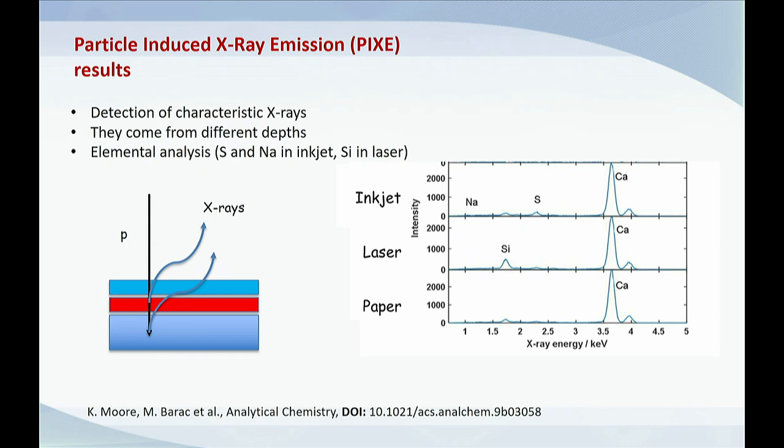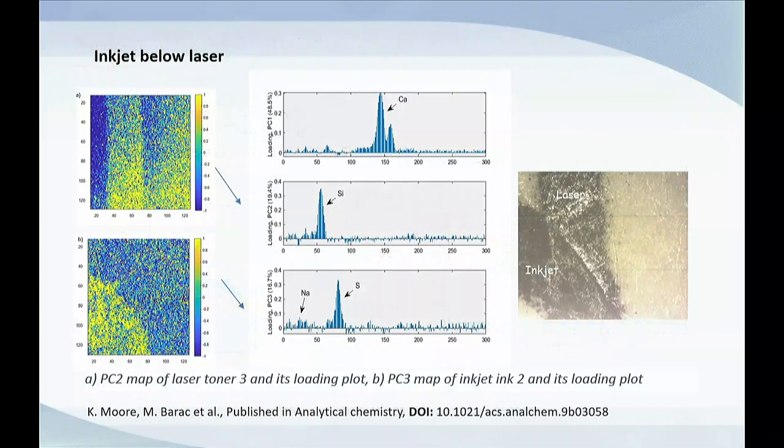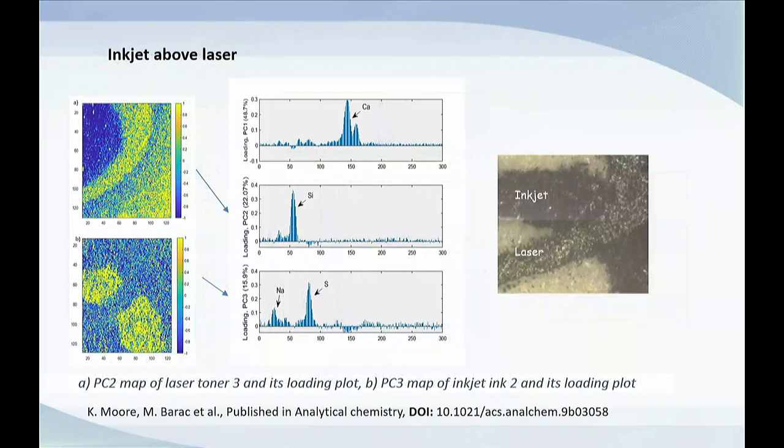And this is just a description of the same thing with PIXE. PIXE integrates all the contribution from all the layers and you cannot distinguish them. Although there are possibilities in X-rays like silicon or sodium, which are absorbed because of their low energies. And this is the same thing done of two different lines from the printer. So you can see in this case, we have inkjet is this one. This is laser. So this is laser jet. And this is inkjet line. So obviously, the laser one is at the top.